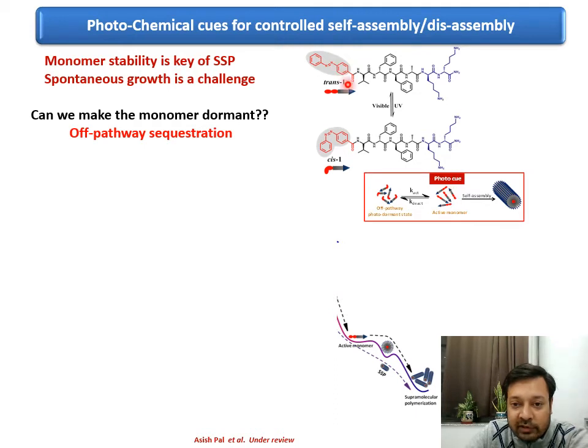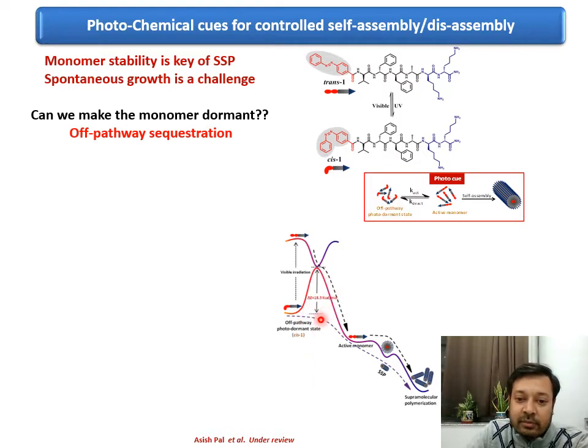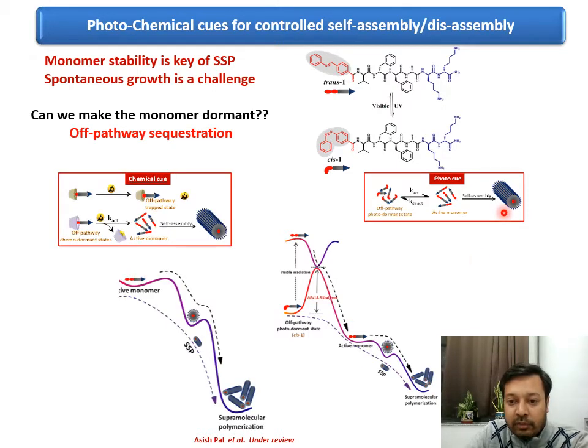So basically you take a trans monomer which is active, and with light it can form supramolecular polymerization. However, if you go into cis, it actually goes into a dormant state, where crossing this activation energy barrier is rather difficult. But at a suitable activating visible light, it can actually come back and you can form this self-assembled supramolecular